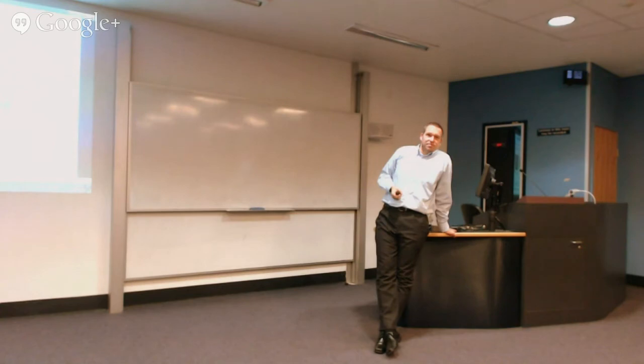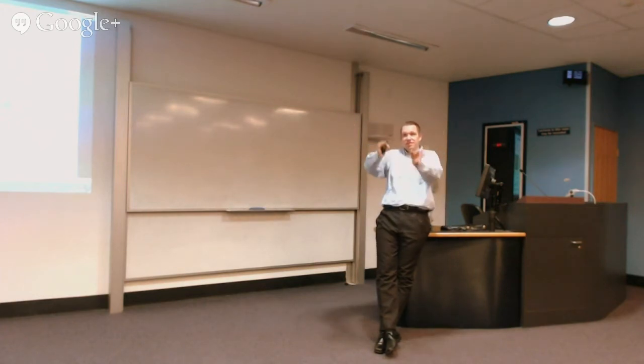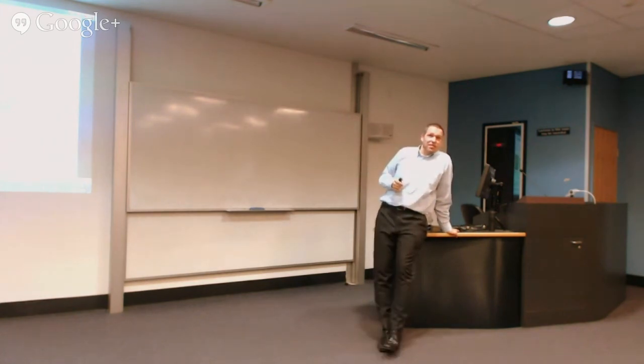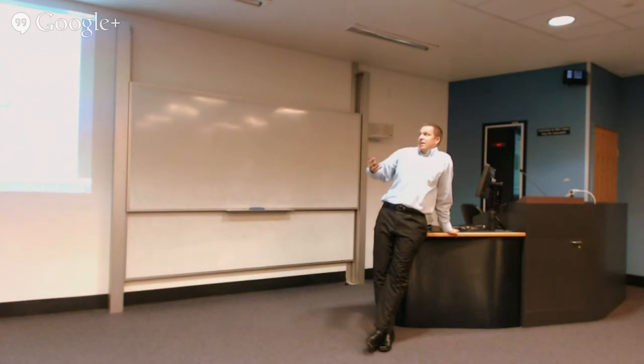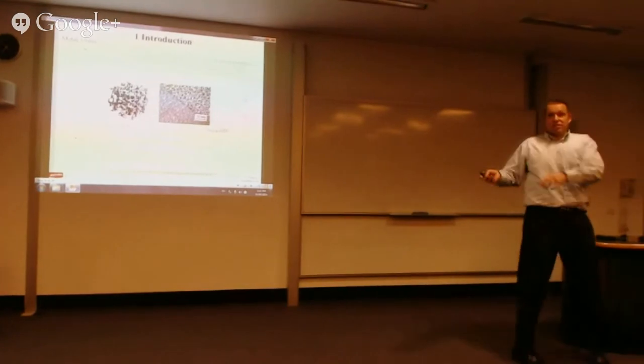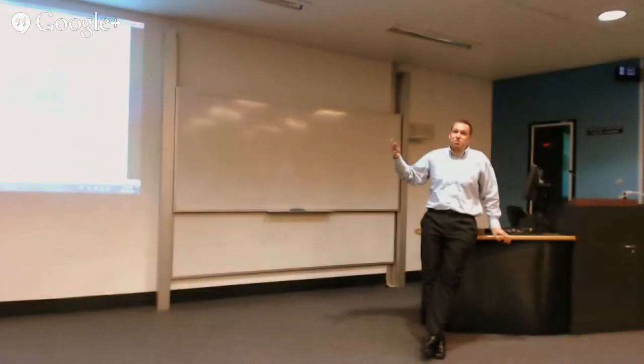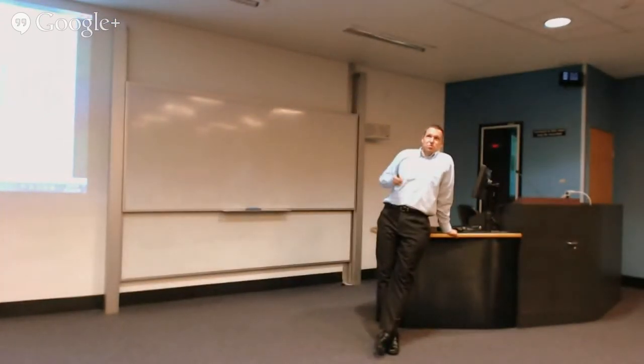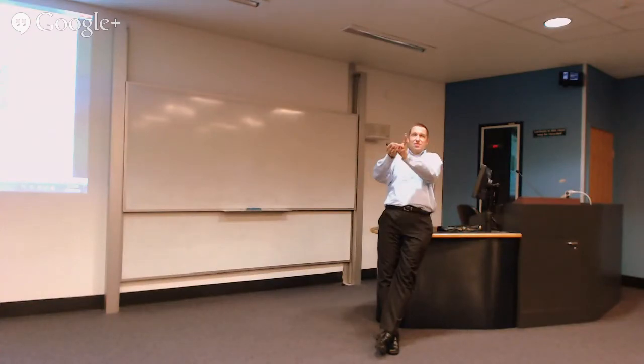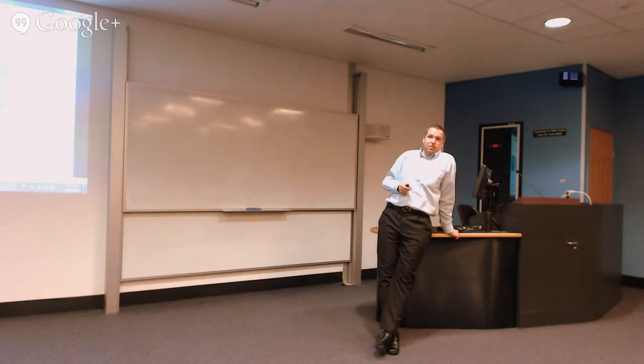And isn't that driven more by the production of material? Sure, there are different manufacturing methods. So we have the material, the structure, and the manufacturing method. Nowadays we are talking rather about printing these materials, either as some kind of polymer materials or metals. So we can even create much more predefined structures, which were 10 years ago not possible. Here you have a heterogeneous structure, because this is from the manufacturing process, to a certain extent adjustable. But with printing, we have nowadays completely different options to clearly define the shape of the structure. So the problem here is the heterogeneous structure. We have some kind of network, but it's very difficult to adjust it. But this can be nowadays solved by 3D printing of metals or other materials.